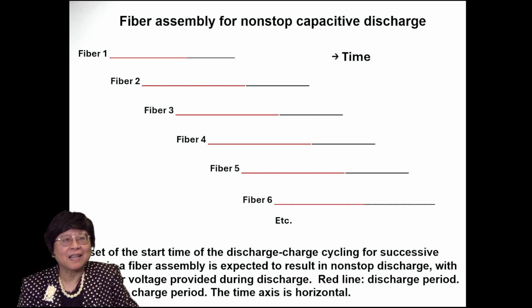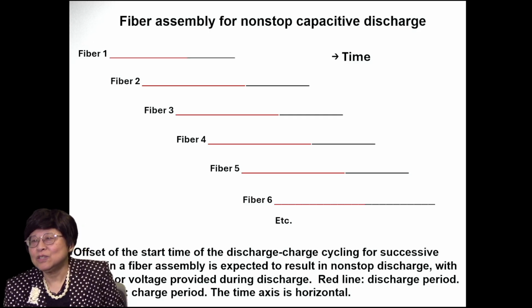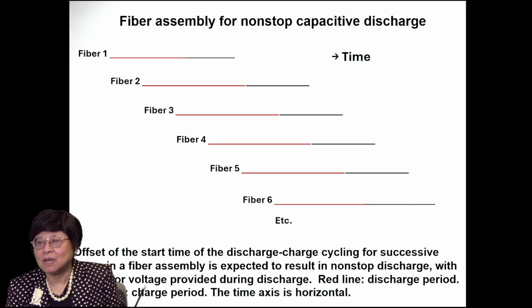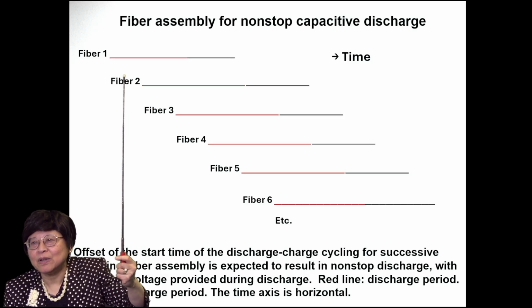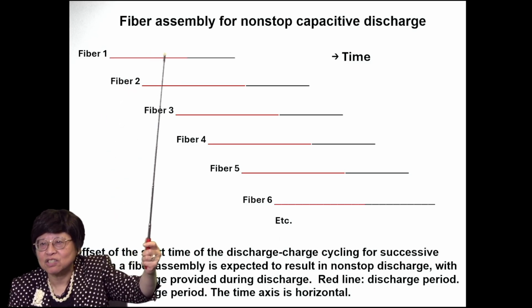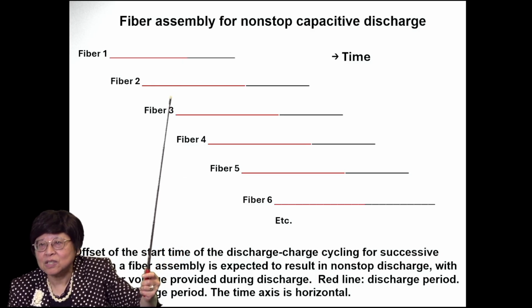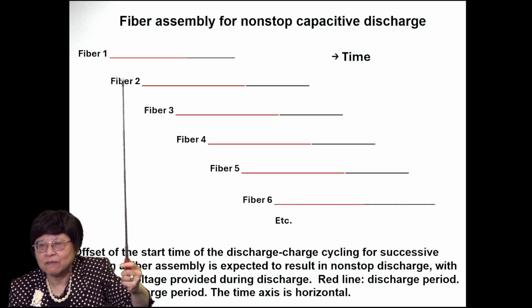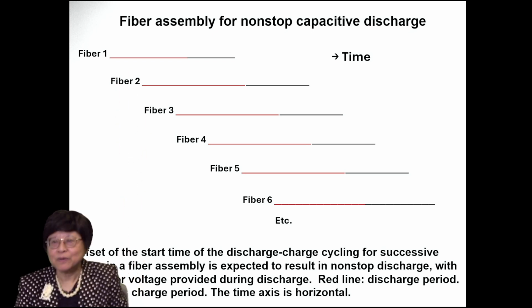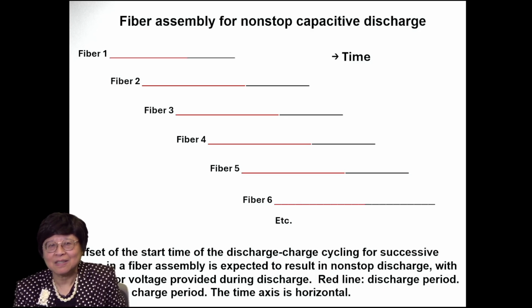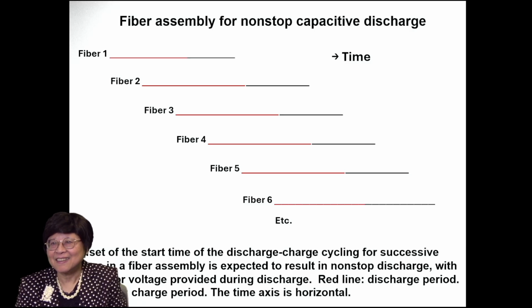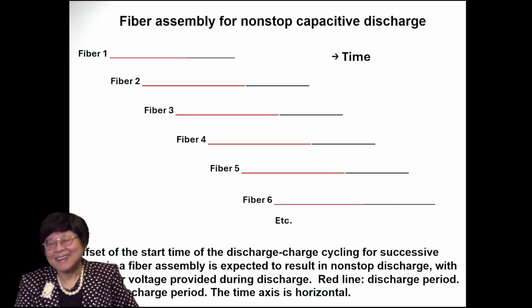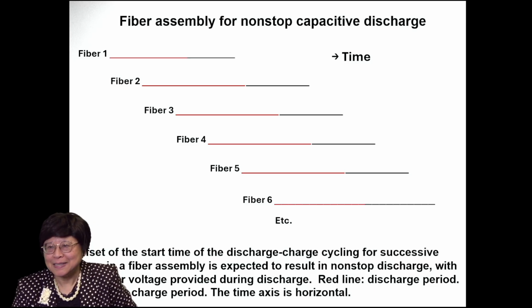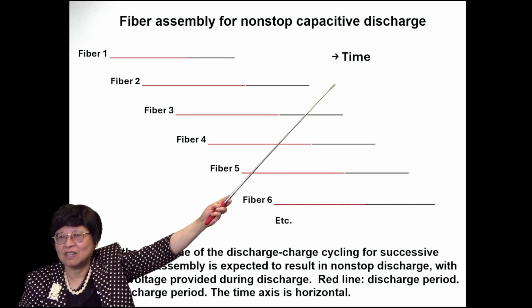This is one application format that we devised, using a fiber assembly. You have fiber 1, fiber 2, and so on. For each fiber, you have a red time period, which is discharge, and then the black time period, which is self-charge. And the start time of the discharge is a little offset between fiber 1, fiber 2, fiber 3, and so on. When you have this assembly of fibers, then you have continuous discharge, and so a continuous rendition of energy. This is perhaps our newest dream, and still a lot of work needs to be done. And note that the time is increasing to the right in this picture.